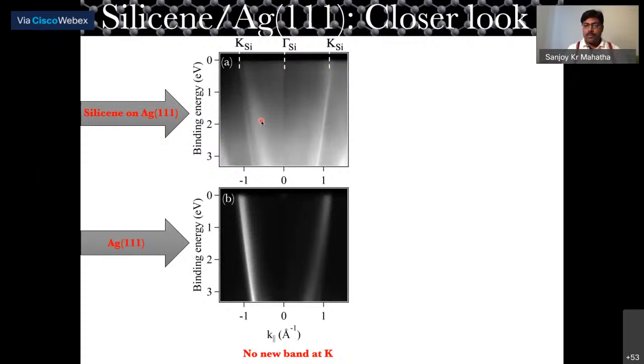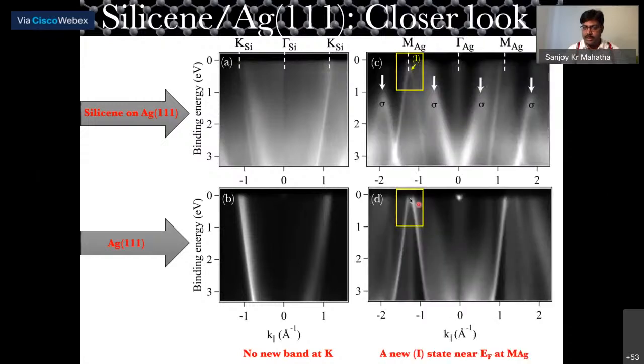Now let's see what happens at the M point of the silver. These are the M symmetry points of the silver. And here you could see that after putting silicon, we also see this kind of parabolic band, which they claimed is coming from silicon. We see this kind of band, and let's assign this band as I. In the following I will explain what this I band is.